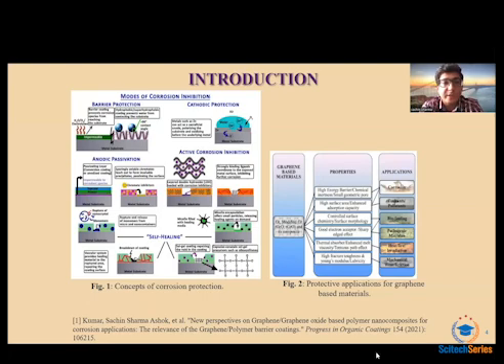The inclusion of graphene nanoparticles into the polymer matrix enhances the barrier properties of the corrosion coatings. Not only graphene, but also graphene oxide and its nanomaterials, and other additives like tin oxide, titanium dioxide, silicon dioxide, zinc oxide, and etc. have enhanced the corrosion protection performance.